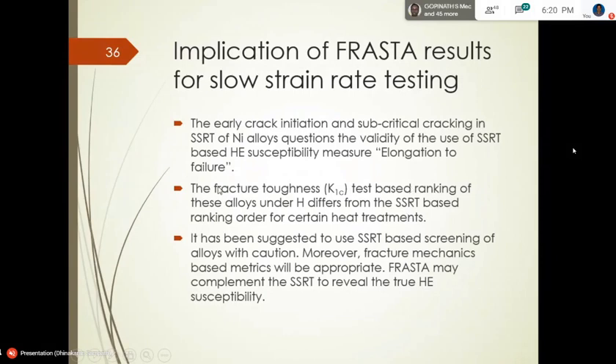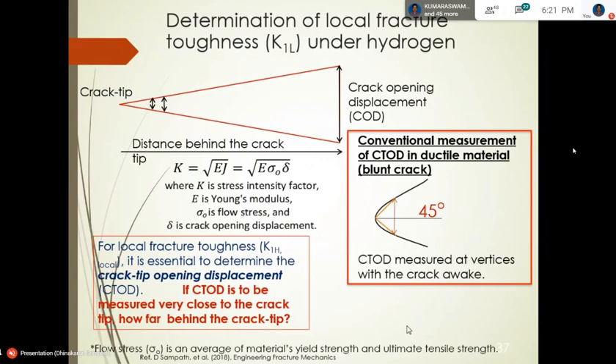And also, we did some fracture toughness tests and compared with the results from SSRT for ranking purposes, and for certain heat treatments we didn't see the same order of ranking. So that's the message. We need to use fracture mechanics, but I think we can also use this FRASTA technique to complement the result. Again, we use the topography to measure the local fracture toughness, which, as I told, is the measure of driving force required for unstable cracking.